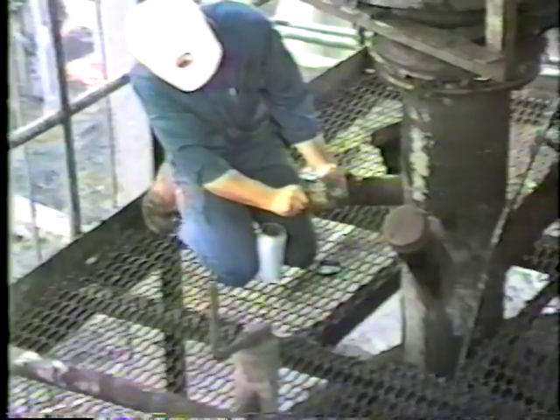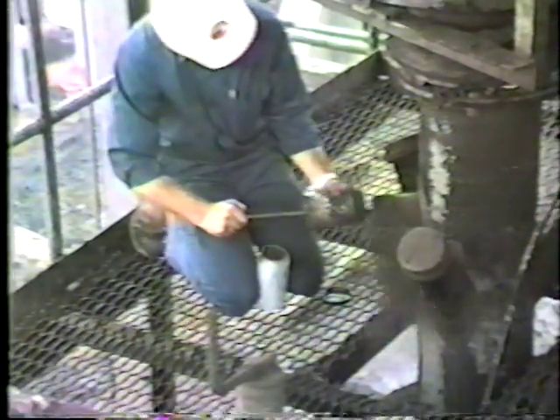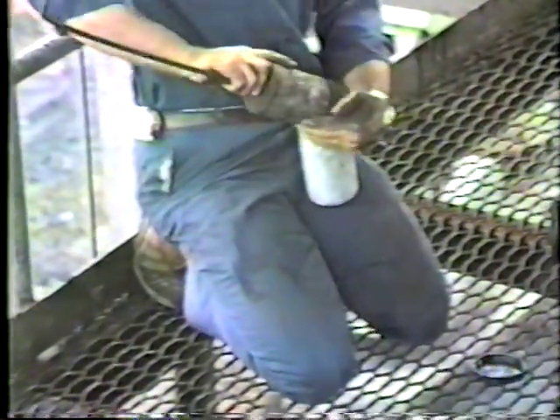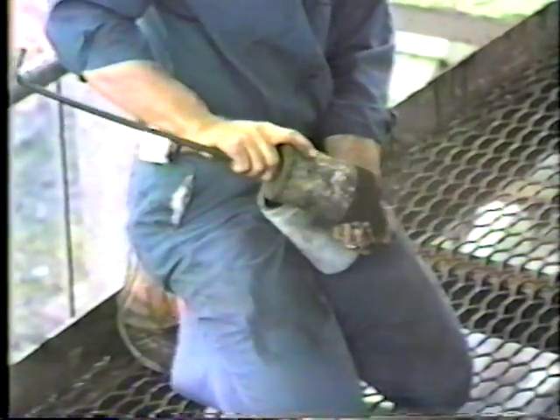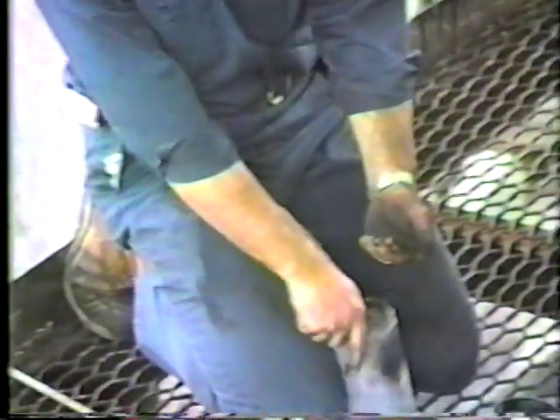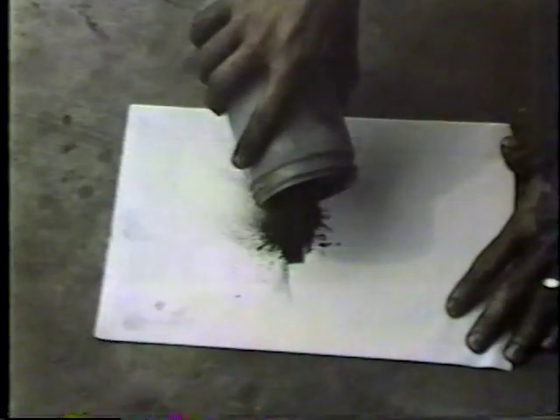The ultra-fine, 98% passing 325 mesh particles, is comparable to talcum powder for fineness. These ultra-fine coal particles remain suspended in the oil after once being mixed, removing the need for chemical additives. Other advantages of this ultrafine particle size is the minimized erosion and abrasion of the customer's boiler system and equipment, as well as the reduction of boiler ash-related problems.